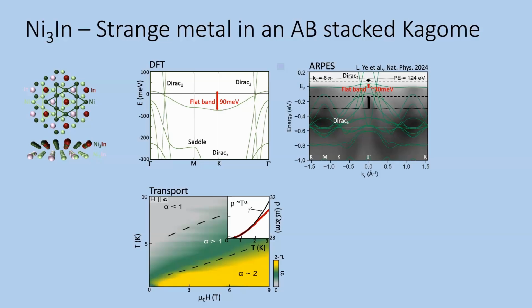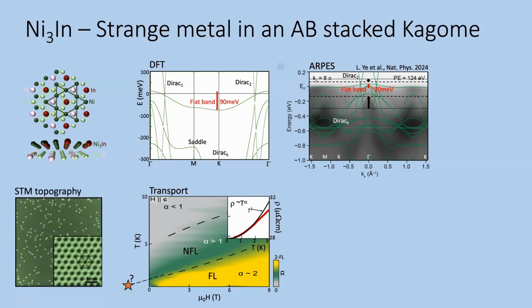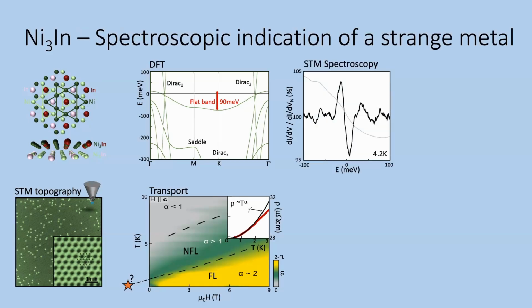So what we wanted to do, of course, since we do scanning tunneling microscopy, is look for the spectroscopic origin of this strange metallic behavior and understand what are the moments in this kagome system. There are no f electronic states. And can we see the strange metal behavior in STM? Right. So this is a topographic image of one of the crystallites that we've measured. This is a thin film of nickel-3 indium, which has amorphous nickel and indium, and among this amorphous structure, there are crystallites of crystalline nickel-3 indium. So we had to sputter, anneal them, and find those crystallite regions. But as you can see, we were successful in doing it, and we can indeed see the kagome surface of nickel-3 indium and take spectroscopic measurements of the surface.